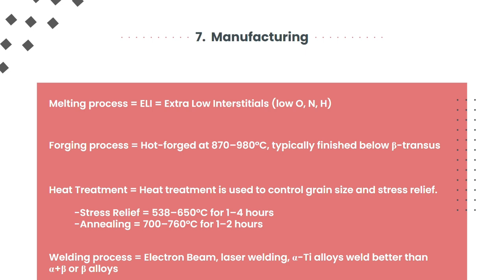And then for our forging process, I would like to mention that it runs at pretty high temperature, as you can tell, almost 1000 Celsius, and it's usually finished before the beta phase. And the heat treatment: for the stress release, we lower the temperature, we let it run for 4 hours, and then for the annealing, we put it back in, and we increase the temperature a little bit for half of the time. And on the welding process, we do some electron beam and laser welding, and just as a fact, alpha titanium usually welds better than the alpha plus beta or beta alloys.